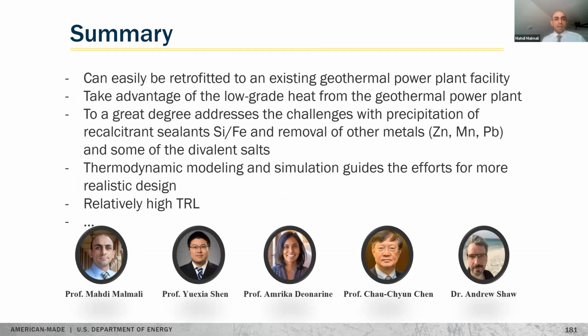So to summarize, we have a very high TRL project, and we think that we can really deal with the high salinity. Of course, we don't have any dependence on water. This process works independent of water. It requires electricity, and green electricity produced in the geothermal plant can be used here. This process also uses the low-grade heat from geothermal brine that has no other use, so it's another value-added benefit. And we can find a way to get around silica, iron, zinc, manganese, and lead, based on the thermodynamic model and process simulations that we have. Everything is going to be validated by thermodynamics and process simulations, energy and mass balance. And the other thing is we are a team of dedicated researchers that we hope can get this technology going. With that, I would be happy to answer any questions.